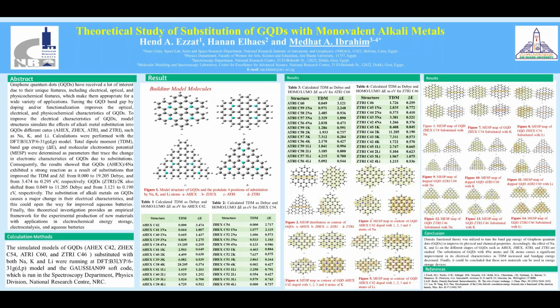Consequently, the results showed that armchair hexagonal graphene quantum dots substituted with 4 sodium atoms exhibited a strong reaction as a result of substitutions that improved the total dipole moment and band gap energy from 0.000 to 19.205 Debye, and from 3.474 to 0.295 electron volts, respectively. Zigzag trigonal graphene quantum dots substituted with 2 potassium atoms also shifted from 0.049 to 11.205 Debye and from 3.121 to 0.190 electron volts, respectively.